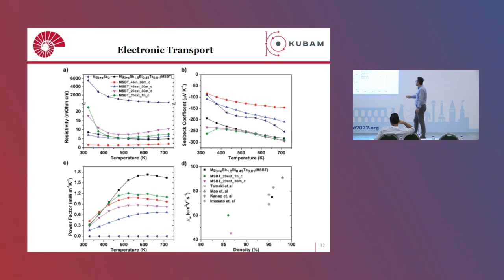So here are the electronic transport characteristics. This is magnesium antimonide. Resistivity is quite high, as you can see. If we dope it with bismuth and tellurium, we can lower the resistivity to here. And then with this melt centrifugation technique, we can also tune the electronic properties together with the Seebeck coefficient. You can see that we have a low Seebeck coefficient with high carrier concentration, or a high Seebeck coefficient with low carrier concentration.